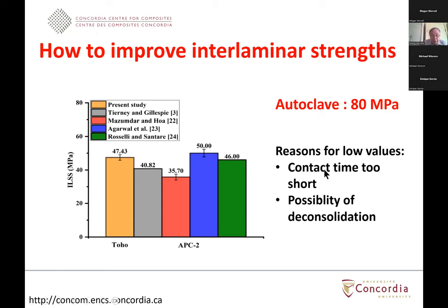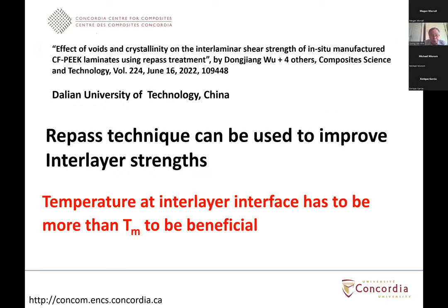One reason for that is because the contact time is too short, in the sense that you have the roller, and because of the speed of the process, the time of contact between the layers is very short. And also there is a possibility of deconsolidation. That means that when the roller moves away from the location and whatever the contact you have, it may be deconsolidated due to the spring back of the fibers inside the layers.